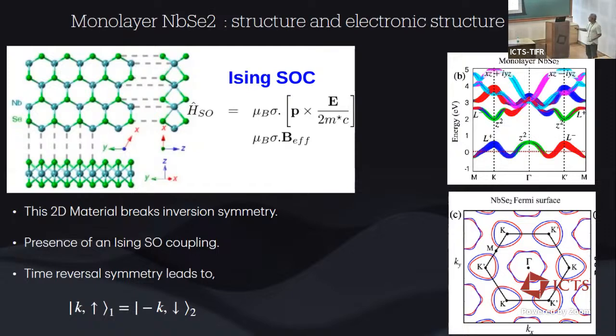Now, this spin-orbit coupling causes a spin-momentum locked structure, and it causes a band splitting in this particular material. And because of this up-down arrangement of the spin, which is different from your Rashba type of interaction, this has been termed as an Ising spin-orbit coupling. Now, what this does is, of course, this is a non-magnetic material, so the Kramers degeneracy has to remain intact.